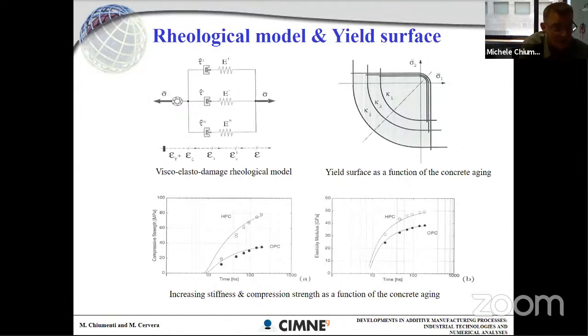metallic alloy, and which is always also the same that is used to generate the mesh for polymer material, also for concrete based additive manufacturing. So we can once again follow the deposition sequence of the concrete and just plug in a new rheological model for this kind of material. Observe that typically these materials are not just concrete as usual concrete for civil engineering construction, but at the moment we are in touch with Acciona, with Aramco and other companies, where the objective is to use even 30% of polymer material into the mixture of this concrete paste. So it is really a new material that must be studied.